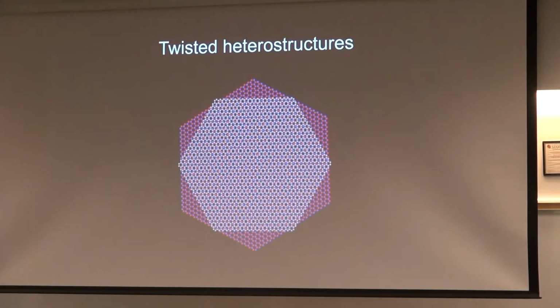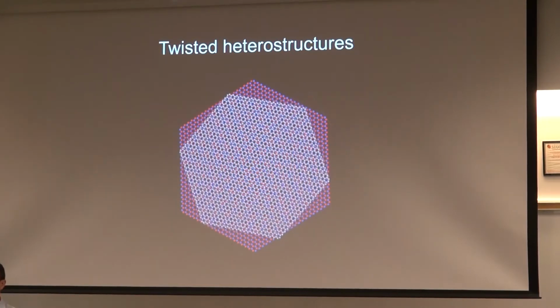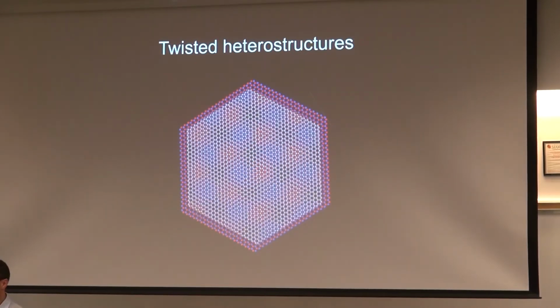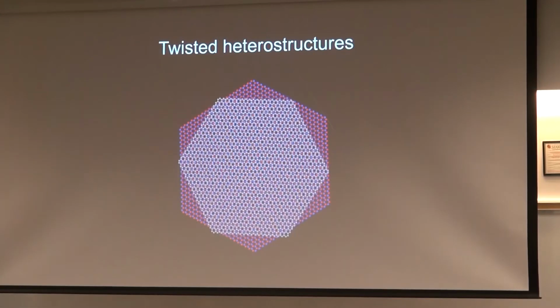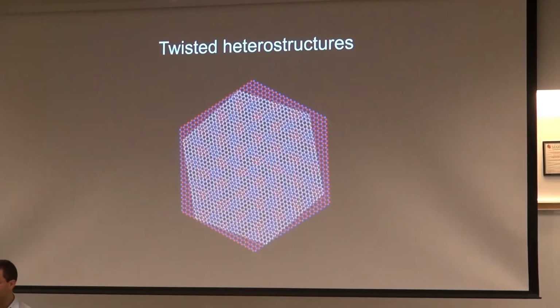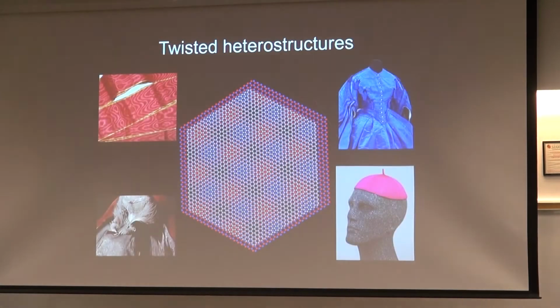You take a graphene and a hexagonal boron nitride, and during the assembly process, you have control over how you put one on top of the other. So you can control the angle between the two relatively carefully. It's somewhat approximate, but it's pretty easy to make these samples, so you can make lots of them, and it's relatively easy to know what the ultimate twist angle is.